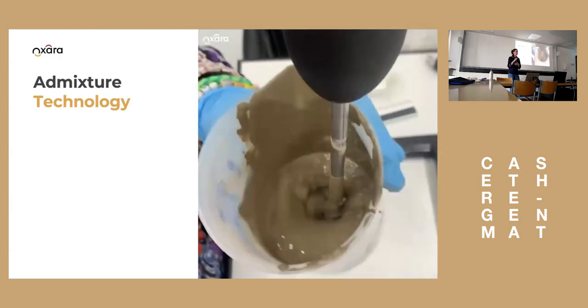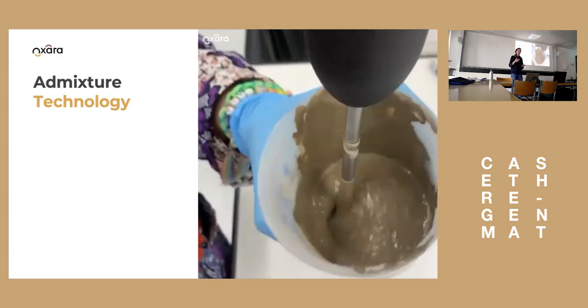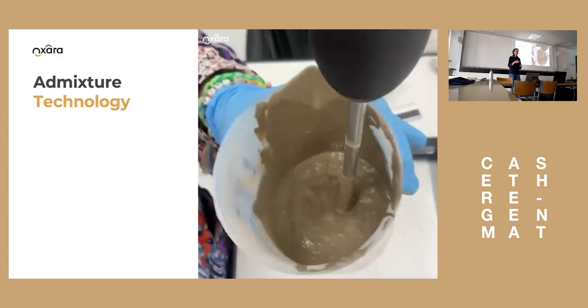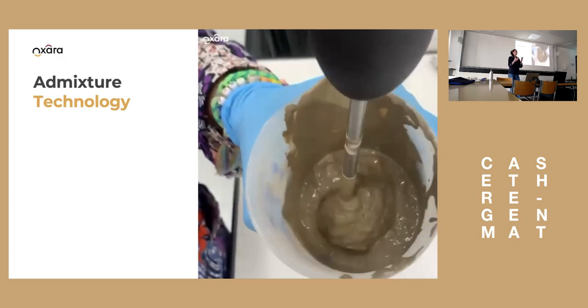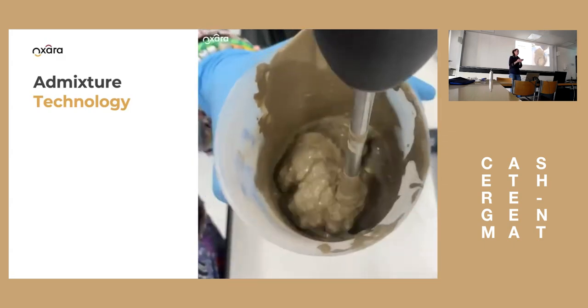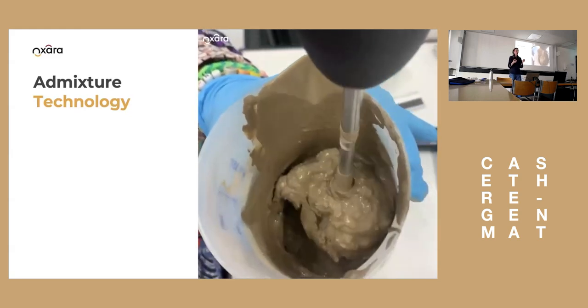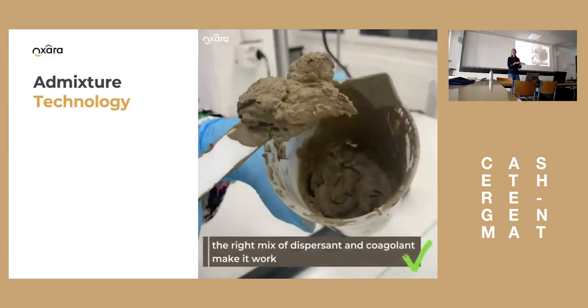Here in this video, for demonstration purposes, we take a coagulant that reacts really fast. As you can see now, it already starts to stiffen. But of course, on the construction site, you don't want such a fast reaction. And it's also not possible to add the coagulant after you place the material. So everything needs to be added in the beginning when you mix the material, which means you need to choose a coagulant that reacts rather slowly so that you have enough time to process the material.